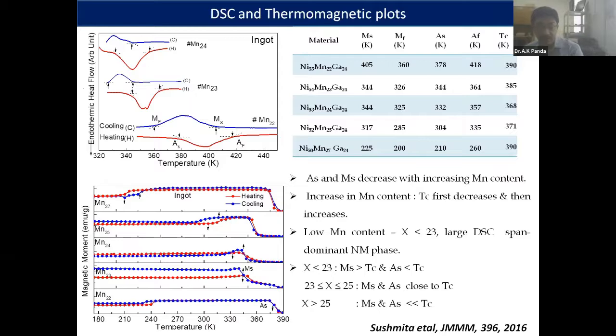These are some of the important findings. We have a large DSC span when we have a low manganese content. When the manganese content is less, the martensitic start temperature is greater than the Curie temperature, and the austenitic start is less than the Curie temperature. So these are the inferences you find comparing the DSC and your thermomagnetic transformations. In the intermediate range, we have the MS and AS very close to the Curie temperature. So by looking at these temperatures, we have to make a choice.